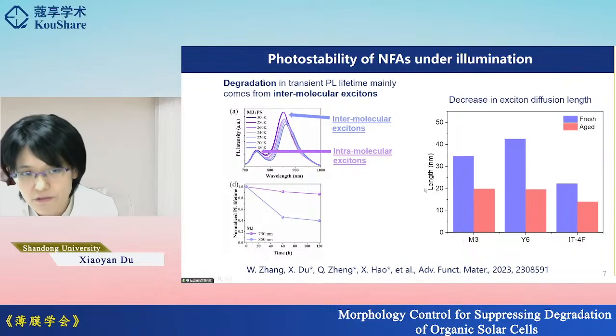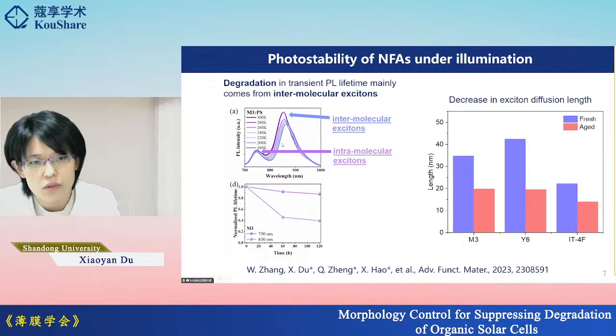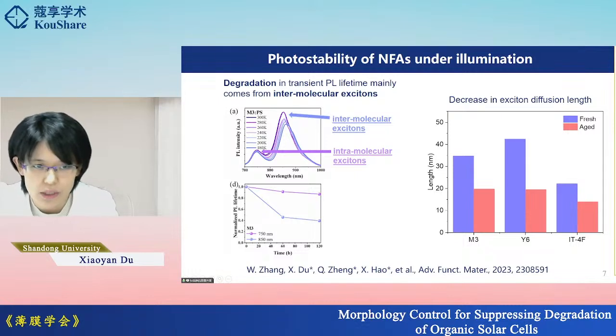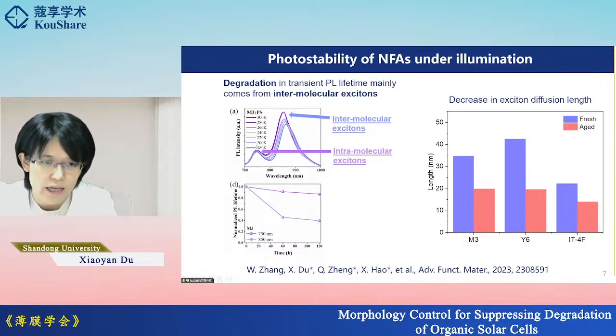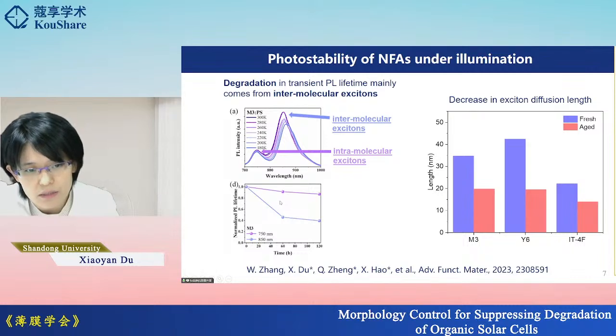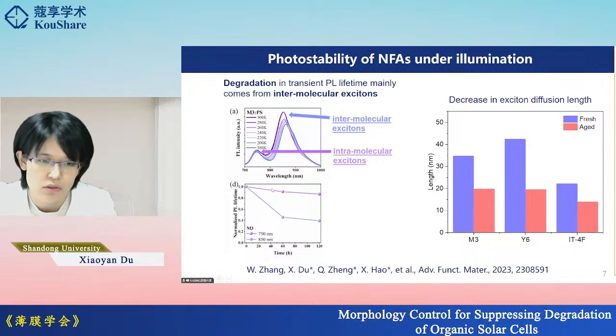solid-state thin films. So in order to look deeper into the degradation origins, we intentionally diluted one of the materials here using polystyrene polymer. So we get two emission peaks. One is from the intramolecular excitons, and the other is from the intermolecular exciton. We can distinguish them not only by the peak position, but also by the temperature dependence behaviors. And for the stability we show here, the degradation in the exciton lifetime is mainly from the aggregated states, while the intramolecular exciton is quite stable.